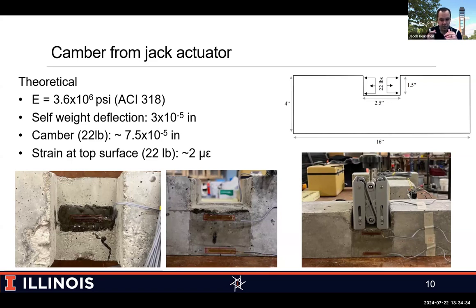This 2 microstrain actually does work out to basically give us plenty of camber to cancel out any deflections due to self-weight. Obviously, if we start to apply loads, then we'll have to apply a lot more load to account for that. But at least with the self-weight, we found that 22 pounds could more than take care of it. So we applied strain gauges right at that top surface where we would expect to see about 2 microstrain. And then we also applied 2 gauges on the side to get the top and bottom, where you would hope that maybe these are going to be equal and opposite.